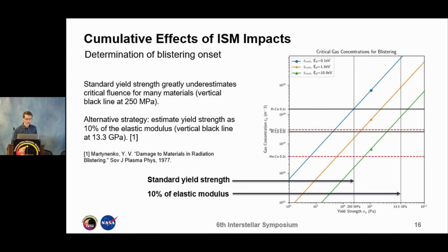This is for copper. An alternative strategy, as also proposed by Martynenko, is to estimate the yield strength as 10% of the elastic modulus, which is the rightmost figure. However, it's important to note that this figure shows the critical gas concentration and thus the fluence threshold for blistering. Bubble formation, swelling, and changes to the material properties are expected at many orders of magnitude lower fluence.